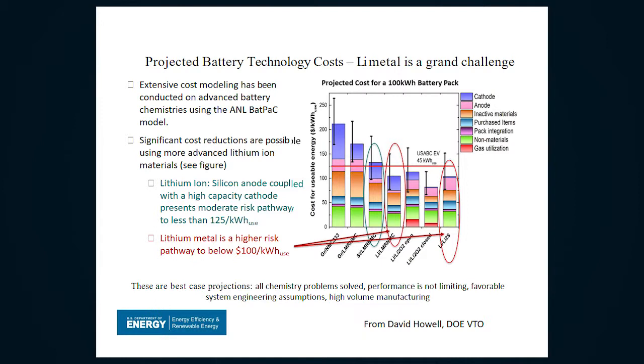Now, if you keep on increasing the energy density of the cathode material, which Wen Zhen will probably talk about later, you reduce the cost. So ideally, if you use a silicon anode, the lithium-ion battery can get pretty close to $100 per kilowatt hour. But if you can use lithium metal, which has the highest specific energy capacity among any electrode material, and then you can couple this with high capacity cathode material, that's probably the lowest cost system we can think about today, if we can make it work.